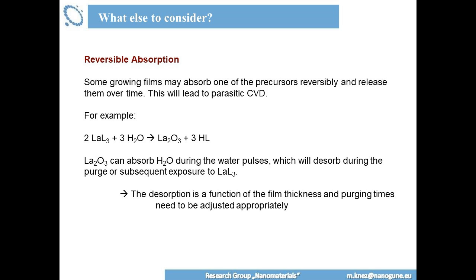In those cases where you have, for example, water absorbed, this water may evaporate during the next cycle. Unintentionally, you bring together the two precursors which are supposed to be separated just because during the next pulse you have from the bottom the next precursor coming, and therefore you have a parasitic growth.